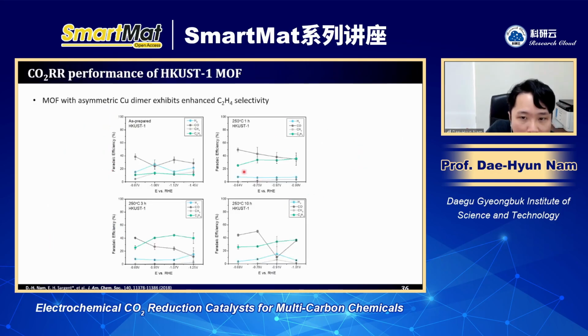And by varying the time of this thermal treatment, we found that some copper dimer asymmetric structures are effective for ethylene production. For example, in the case of the symmetric copper dimer, the major products were hydrogen and some CO. But if we detach some carboxylate groups to make the copper dimer asymmetric, we found the ethylene FE increased.